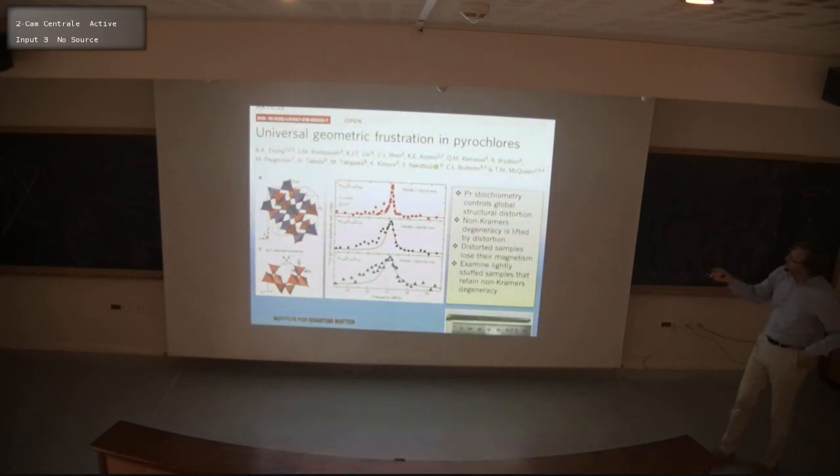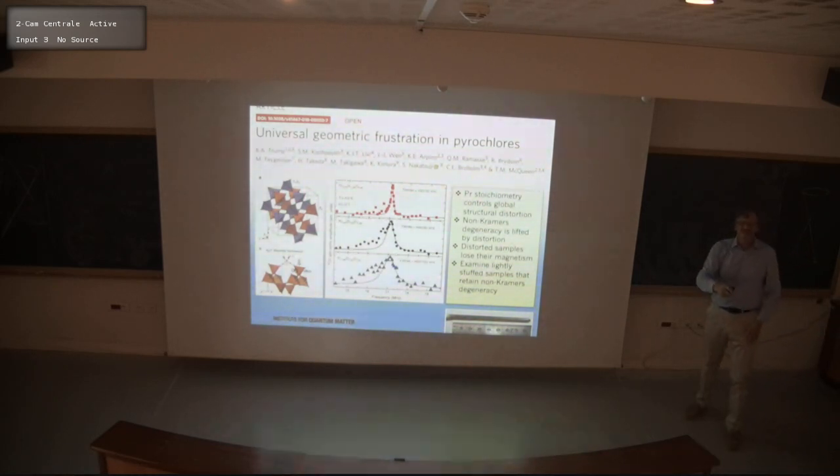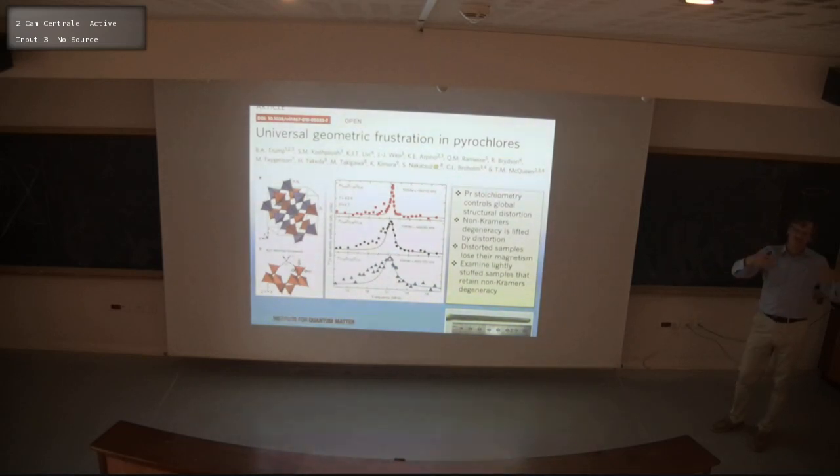There's another part of it, which is that this pyrochlore crystal structure has a certain kind of instability called a beta cristobalite distortion, which Tyrell has indicated here, where each tetrahedron rotates a bit with respect to its neighbor. That lowers the symmetry at the praseodymium site and therefore introduces a splitting of that doublet degeneracy. So it drives the system into a singlet ground state, a local singlet ground state system.